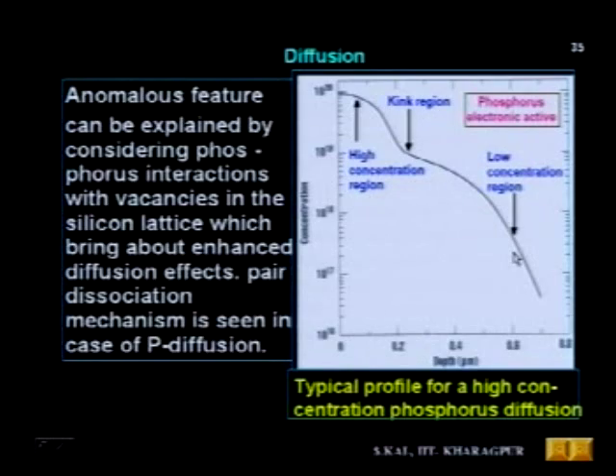Normally, pre-deposition diffusion is a constant source diffusion, and you normally get the error function profile. Here it is not similar to the error function profile, something different, and that has been observed in case of phosphorus, not in case of arsenic or antimony. So the flat region, next a kink region, and a broad tail. That is the difference from the normal arsenic or antimony pre-diffusion profile. The anomalous feature can be explained by considering phosphorus interactions with vacancies in the silicon lattice, which bring about enhanced diffusion effects. Pair dissociation mechanism is seen in case of phosphorus diffusion also. That is the reason for this anomalous behavior.